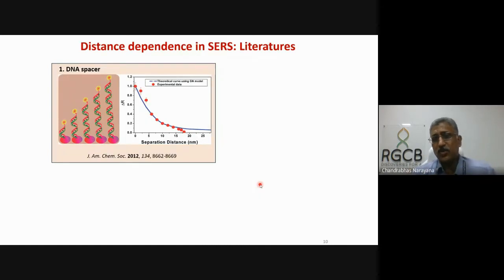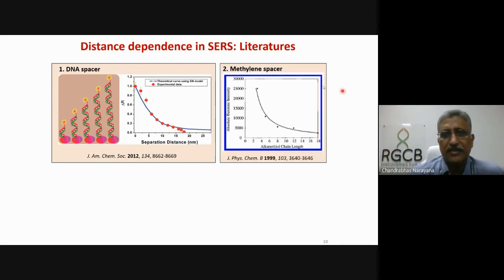So people have been interested in knowing how far the molecule can be. One of the ways people did this is by looking at DNA, which can be very exactly measured. How much is the distance between the molecule and the gold nanoparticle? They did this experiment and found that it can actually go up to 15 nanometers, or 10 nanometers you can actually detect, which was unusual. People couldn't realize. So people then went, instead of DNA, to methylene spacers, that means CH2, CH2, CH2. And again, they found that this was giving you around 10 to 12 nanometers as the length to which the molecule can be kept.